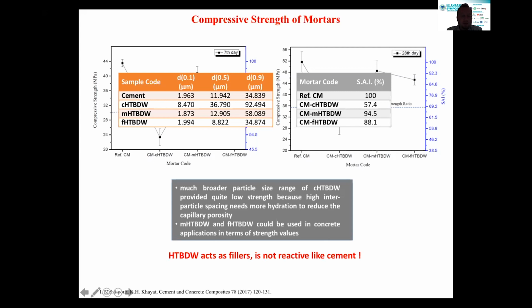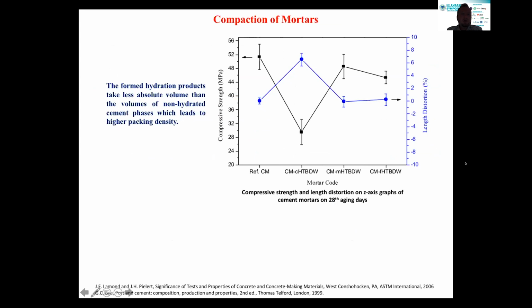It's important that the heat-treated waste acts as a filler, but is not reactive like cement, because with the addition of the heat-treated waste powder, we have a little bit of loss in the compressive strength, even for the medium and fine powders. With the aging time, the cement mortars get more compaction. I mean, the formation of the hydrated products leads to higher packing density in the cement mortar. So there is an opposite relationship between the compressive strength and the length distortion.